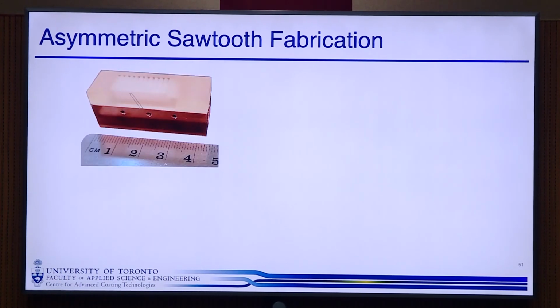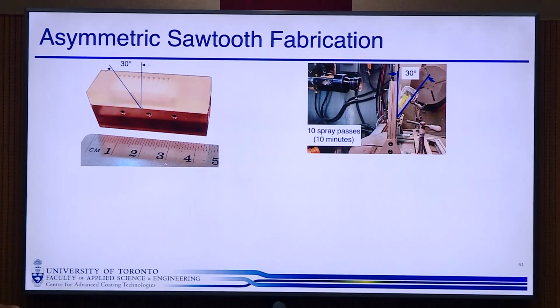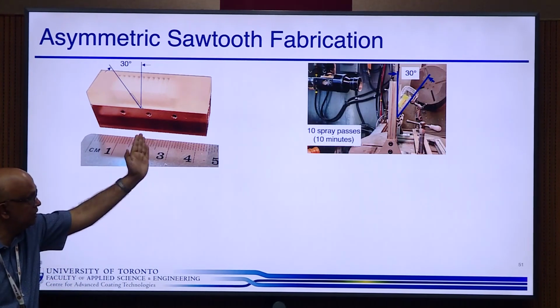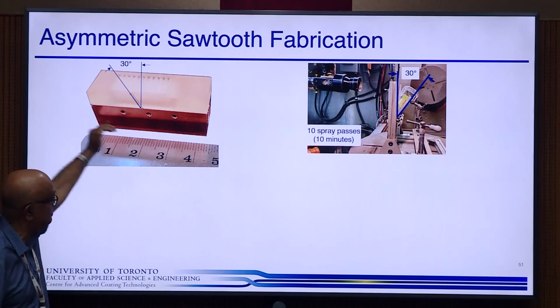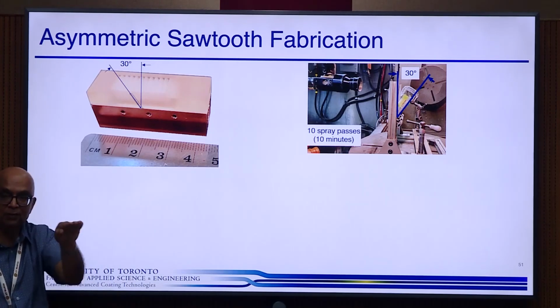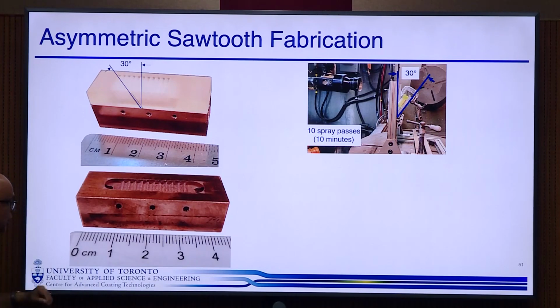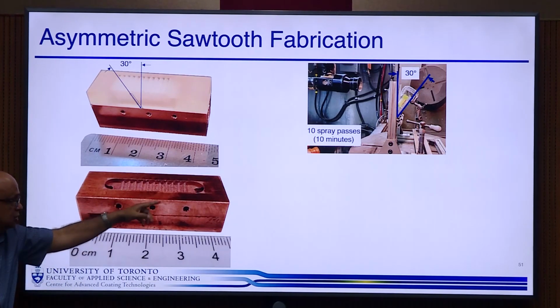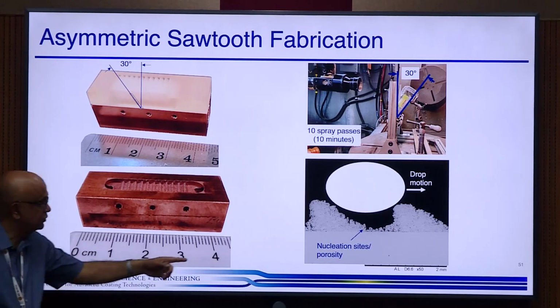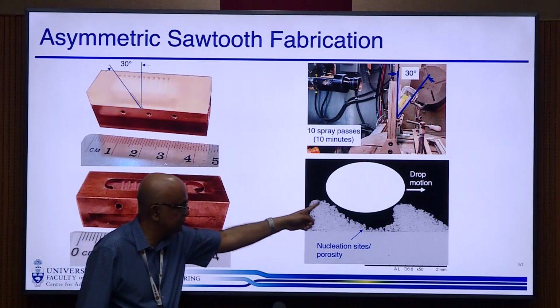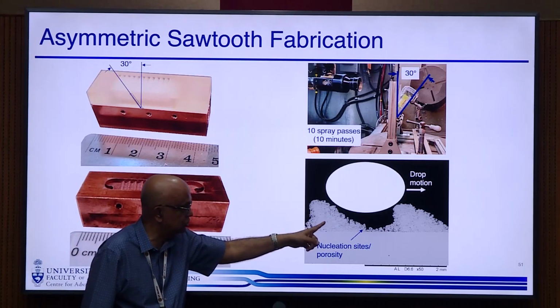So what we did is we made a mask, but we've got the openings inclined at 30 degrees. And so all of those openings are at 30 degrees. And then we set this up and we incline the surface at 30 degrees. So we are spraying along the openings. And what you end up with is a structure like this. And if you take a cross section of that, you've got this sort of sawtooth structure.